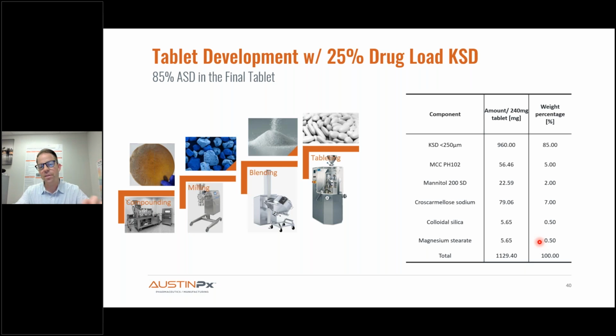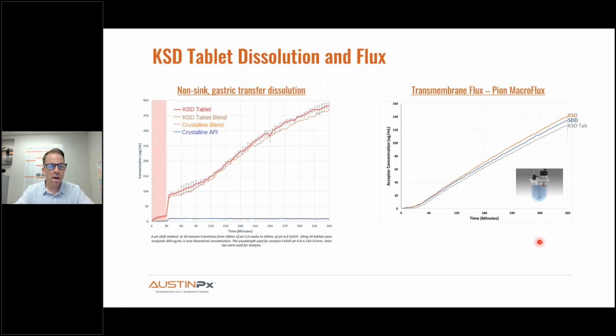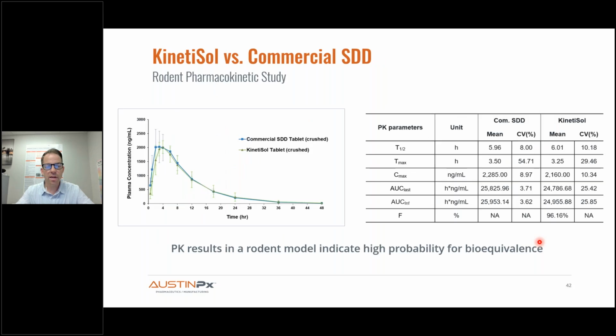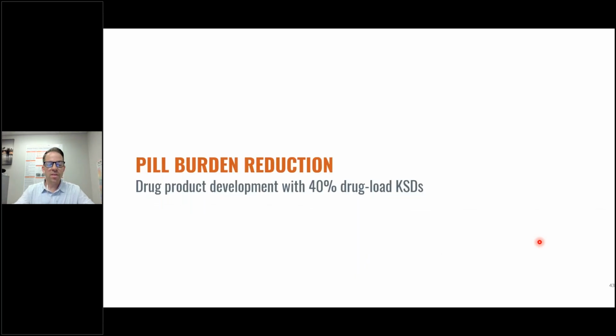So a little smaller tablet size at the same drug load. Again, looking at using our biopharmaceutical tools, similar dissolution and flux profiles between the tablets. And then finally, we went into an in vivo PK model and established bioequivalence of the KinetiSol formulation to the commercial SDD tablet. But with that, we wanted to further reduce pill burden.